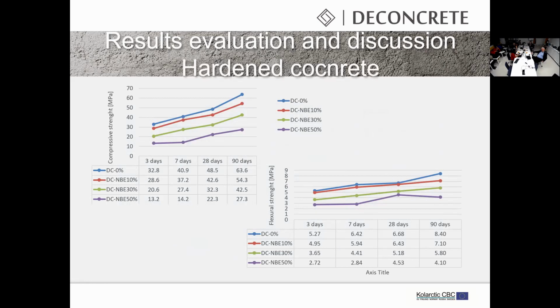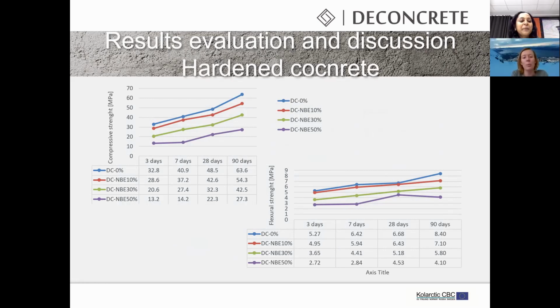Some data from the hardened testing. I gave an example of the NBE type, 10, 30, 50% replacement, compared to the reference mix purely with cement. There is an obvious reduction of the compressive and also flexural strength. Nevertheless, the 10% replacement doesn't have a significant effect on strength, and follows the development of strength of the reference sample.